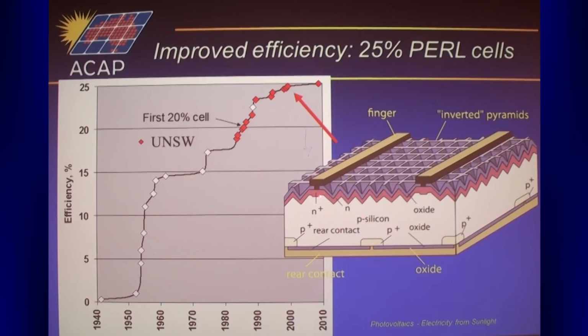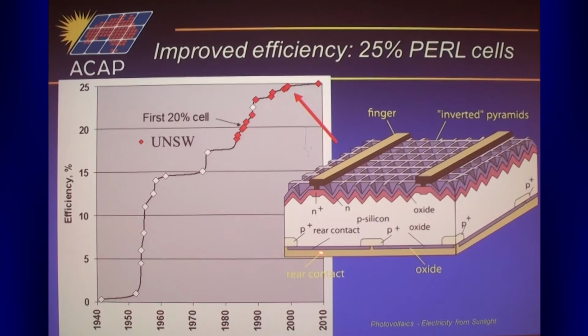So we've incorporated that in the front side, so wherever we have a metal contact, it's protected by this heavily doped region that stops the minority carriers from getting there, and then applied to the rear as well. And then we use oxide enshroudment to passivate the whole surface. An additional refinement here is that we use the electrostatic effect of this rear contact to control the recombination in this intermediate region here. But I won't have time to go into that.